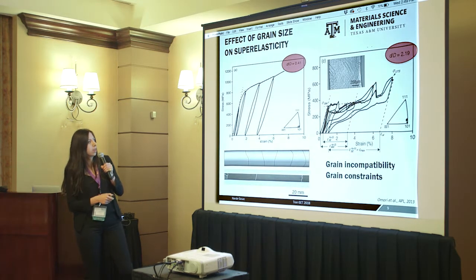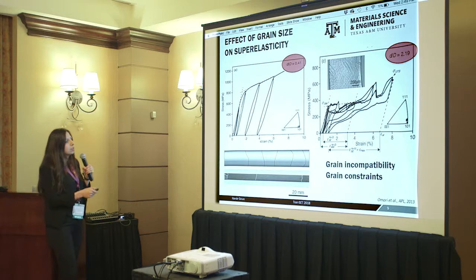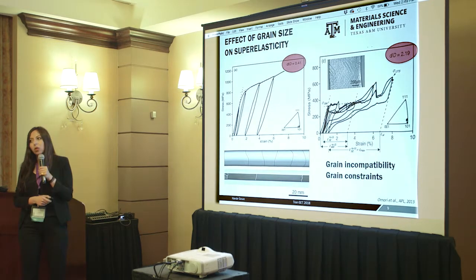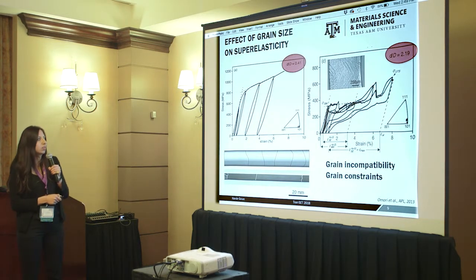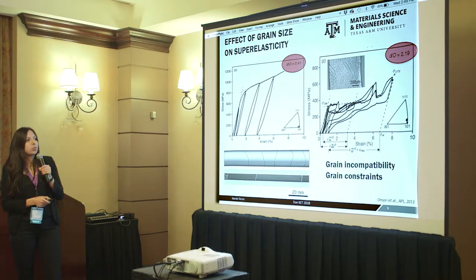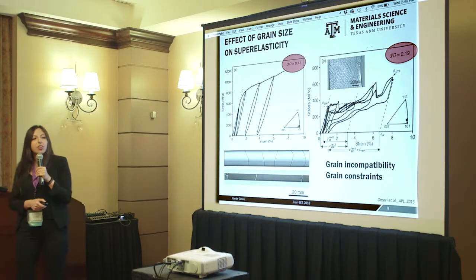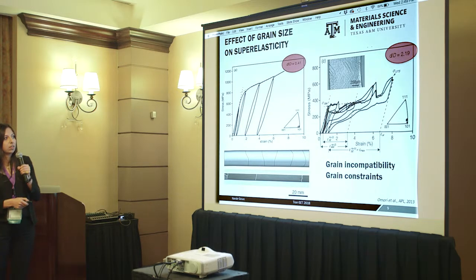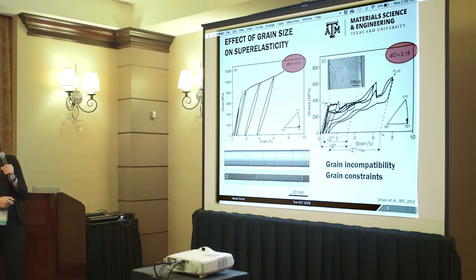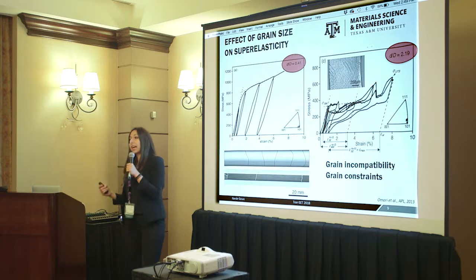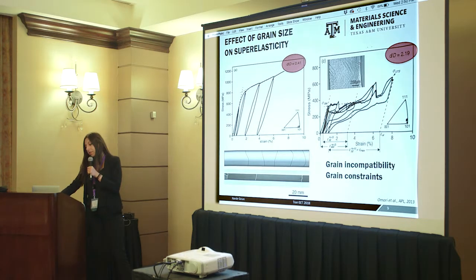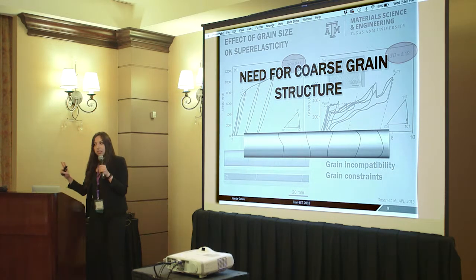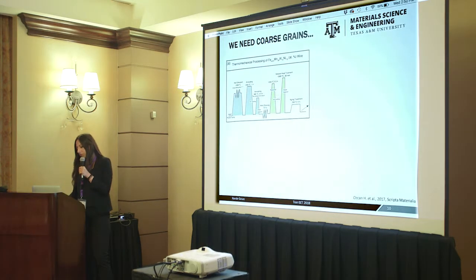These two graphs show this very clearly. This is the response of a wire with a small grain size, and this is the response of a wire with a large grain size. As we increase the grain size, we start to see superelasticity and the wire can recover deformation. Again, if your grain size is small, your material is not going to work. So the second thing we need is a coarse grain structure.